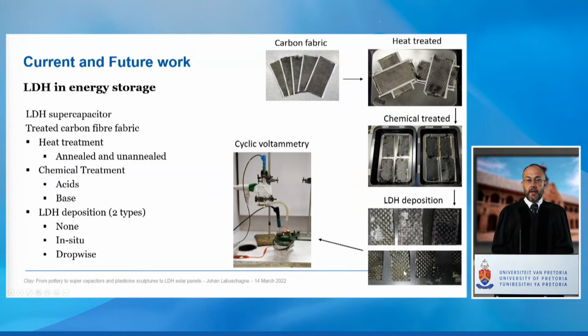We heat treated it, some of them we didn't. We did chemical treatment of the heat treated samples. Some we didn't treat, some we did treat. And then we did LDH deposit on some of the samples where some of the other ones we didn't. We then did cyclic voltammetry to investigate the capacitor behavior of these samples.